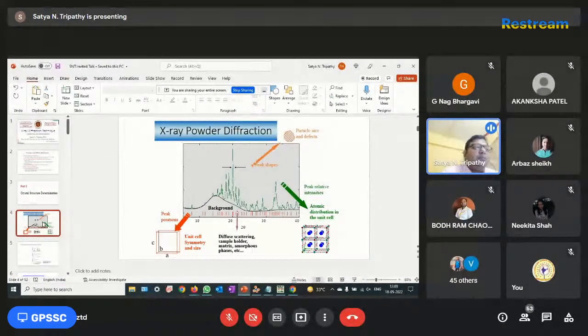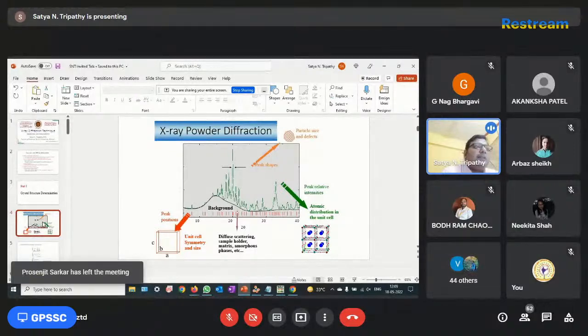From the peak positions we can calculate the unit cell size. From the intensity we can calculate the atomic distribution in the unit cell, basically from the structure factor point of view. And from the peak shape, we can calculate the particle size and strain effects. So these are the basic information we can calculate.